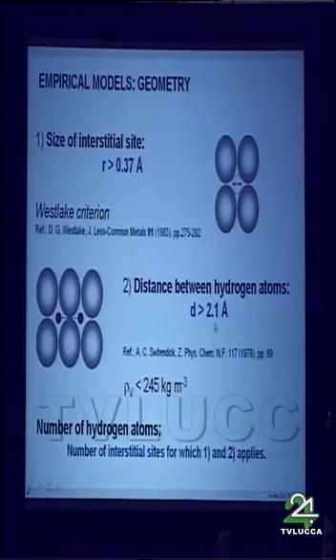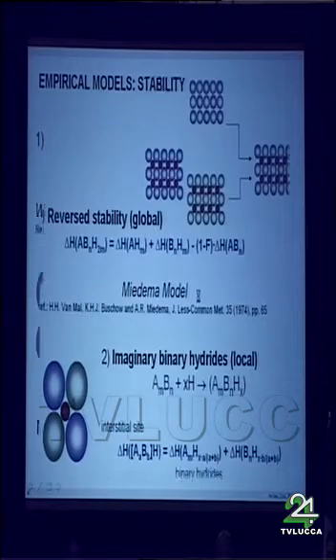Now, if we assume that this would always be the case, we can calculate the theoretical maximum volumetric hydrogen density in such a system, and that is 245 kilograms per cubic meter. Now, this is interesting because the best hydrides, or the hydrides with the highest volumetric density we know today, have about 150 kilograms per cubic meter of hydrogen. So there is still a huge potential for improvement if this criterion really applies to all the systems. And in order to estimate the number of hydrogen atoms we can bring into a lattice, we count the number of interstitial sites for which these two criteria apply, and then we have the maximum number of hydrogen in the lattice.